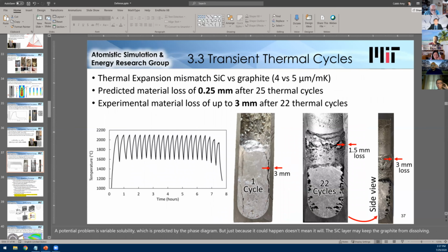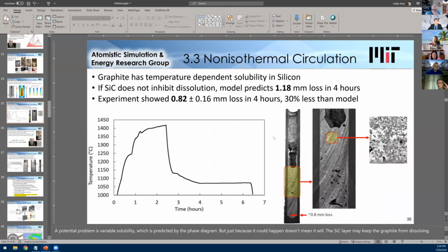So this slide, which is related to thermal cycling issues, is probably addressable. And it's an interesting slide because it's relevant to a related technology that several people are still working on, like Alejandro Datas, which is latent storage with silicon at 1400 Celsius. They intentionally thermal cycle every day, with phase change actually, which is even worse, so they may experience this issue. The problem shown here is in a way inconclusive because this experiment was run very quickly. So it's not obvious that you would get delamination if you thermal cycled more slowly. So there's a potential solution to this problem.